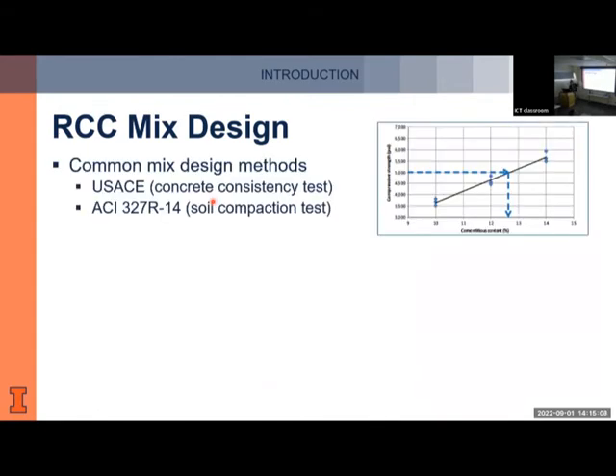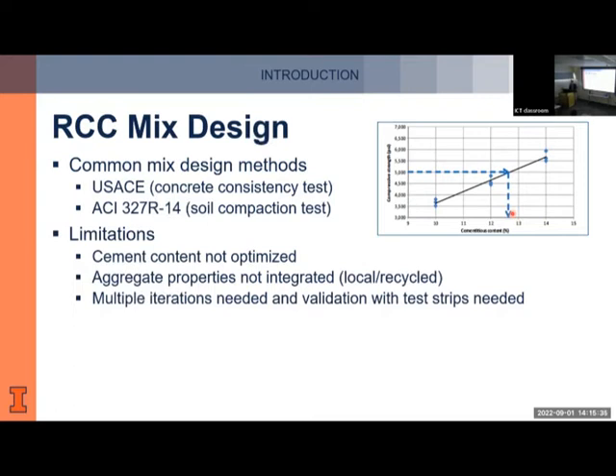How do we currently design RCC mixtures? There are two methods: the Army Corps of Engineers method, based on concrete consistency, and the ACI method, based on cementitious content and compressive strength. If you aim for 5,000 PSI for your RCC pavement, the chart tells you to use about 12.6% cement — it's very empirical and subjective. The cement content is not optimized for your aggregates, the aggregate properties are not integrated, and contractors sometimes haul a known aggregate source over long distances rather than use local or recycled aggregates, which costs money and causes delays.